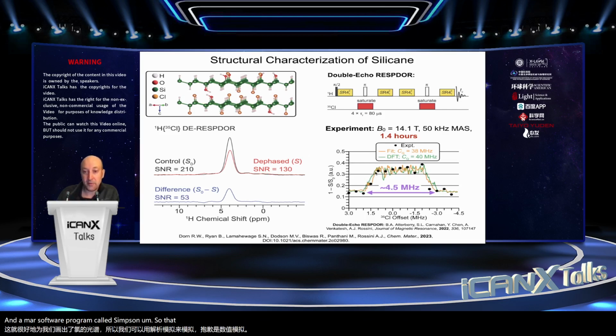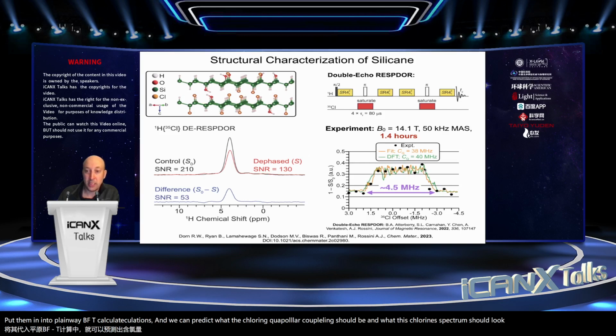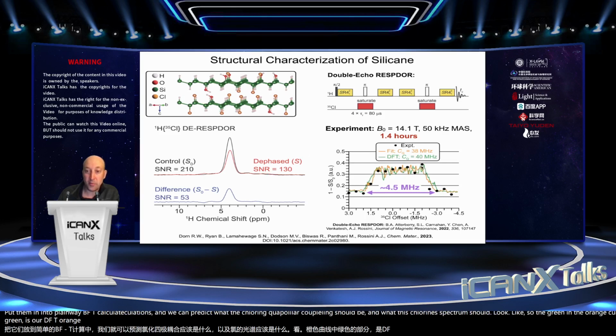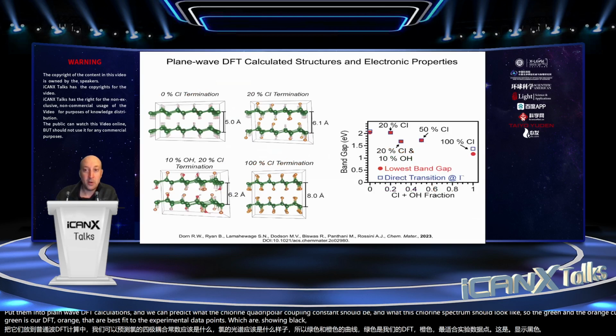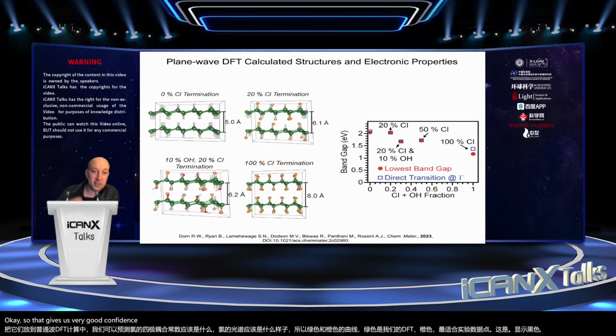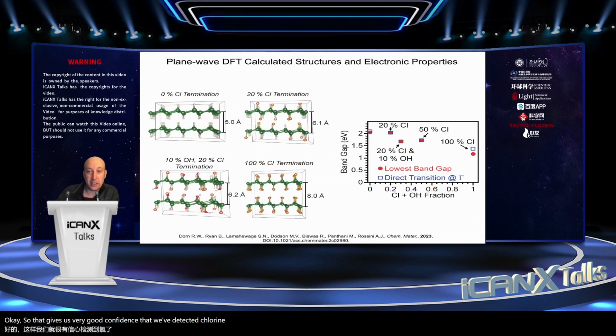So that's our fit. And then furthermore, what we can do is take structural models like this, put them into plane wave DFT calculations, and we can predict what the chlorine quadrupolar coupling constant should be and what this chlorine spectrum should look like. So the green and the orange curve, green is our DFT, orange is our best fit to the experimental data points, which are shown in black. Okay, so that gives us very good confidence that we've detected covalent chlorine in this material.